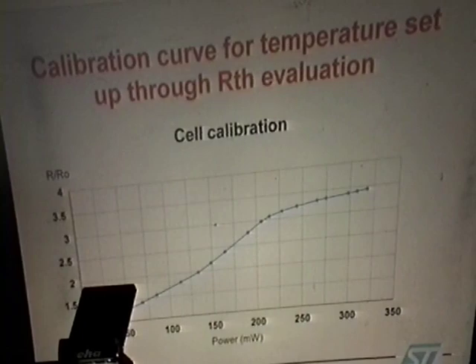And this is the calibration curve for the cell. It's not possible to measure easily the temperature of the film, so we need a calibration done before starting the experiment. And the nickel shows a change of phase at 360 degrees when it loses the ferromagnetic properties. So it's quite easy to understand how much power we need to reach that temperature. And usually the ratio between the resistance and the R0 resistance is around 3.